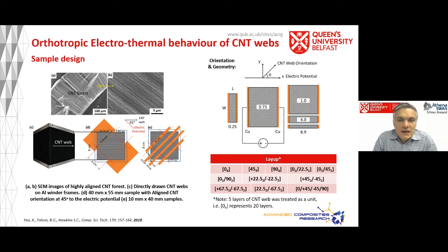And I should mention that the way we grow them, as you saw from that video, they're pretty transparent. I think there's an 80% optical transmissibility. And so you've got those two parameters, but then because these are so highly directional, they have orthotropic behavior, so that their conductivity along the carbon nanotube draw direction is very different to the conductivity orthogonal to that, just like the stiffness and strength characteristics of a carbon fiber ply.